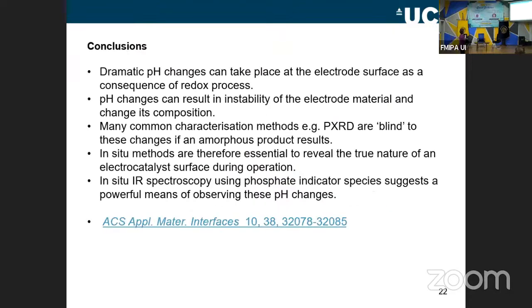So to come to my conclusions, I hope that I've shown you that you can see quite dramatic pH changes at the electrode surface because of redox reactions, if they produce hydroxide or if they produce protons. If this happens, then your electrode material can become unstable if you don't choose a material that is stable at different pHs, and it might change its composition.